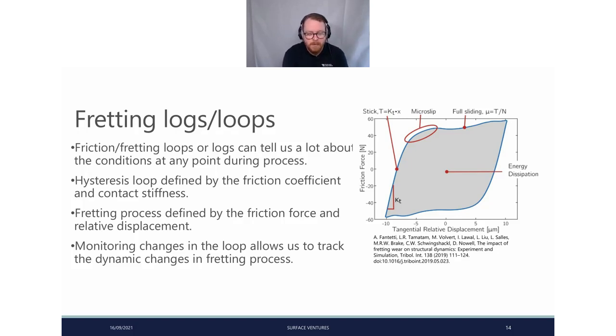Our contact stiffness we normally measure by the gradient, just at our change in displacement. So you can either do this at the far right or the far left, and then you can see your micro slip as it changes direction. We have full sliding right at the top. So if we look at the values of friction at the very top and bottom, we can then use that and find what our root mean square friction is for these, and that can give us our friction during sliding. So that's for the hysteresis loop.